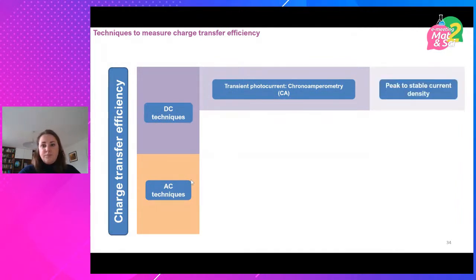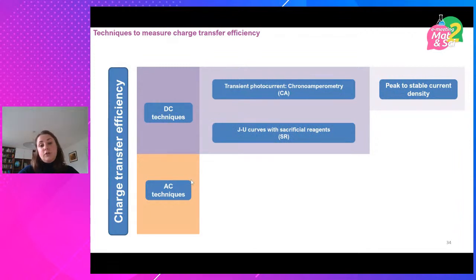So Frankie, unlike me, I investigated only 3 electrode samples. Frankie made 20. And for each and every one of those samples, he computed the charge transfer efficiency using a myriad of different techniques. So he used some DC techniques and some AC techniques, and he got really excited. For DC techniques, he used transient photocurrent. So this is the chopped photocurrent that I just showed a slide ago. And from there, you can see the difference between the current spike from the rush of charge to the stable, constant photocurrent that flows. And then you can also do things like recording photocurrent as a function of applied potential when you put, for example, a scavenger into the solution. So that could be used to determine the bulk recombination ratio relative to when you don't have sacrificial reagents.